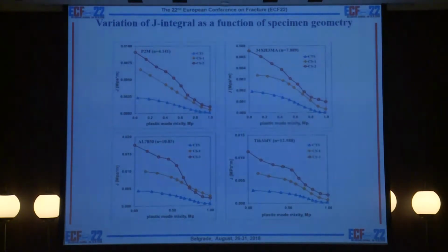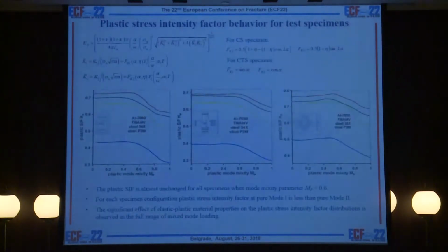Again, you can see distributions of the J-integral as a function of specimen geometry. You can see that the J-integral is very sensitive to the constraint effects. In this figure, you can see results of calculation of the plastic stress intensity factor for each considered test specimen. Again, I would like to pay your attention that in a range of mixed modes when MP is lower than 0.6, the plastic stress intensity factor is almost unchanged. And of course, a significant effect of elastic plastic material properties on the plastic stress intensity factor distributions is observed in the full range of mixed mode loading.